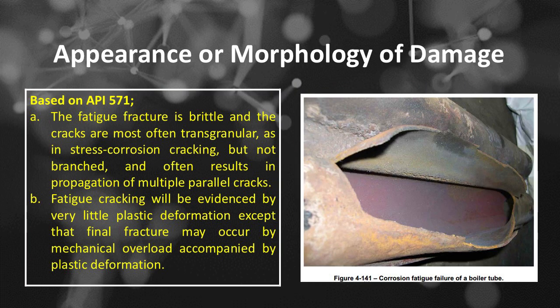Appearance or morphology of corrosion fatigue damage based on API 571. Number A, the fatigue fracture is brittle and the cracks are most often transgranular, as in stress corrosion cracking, but not branched, and often results in propagation of multiple parallel cracks. Number B, fatigue cracking will be evidenced by very little plastic deformation, except that final fracture may occur by mechanical overload accompanied by plastic deformation.